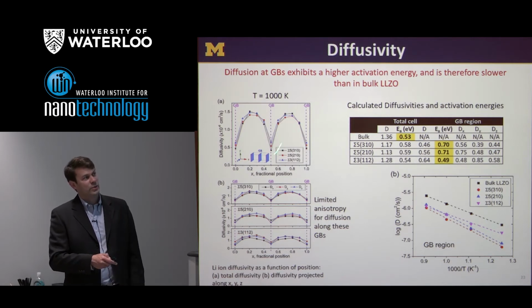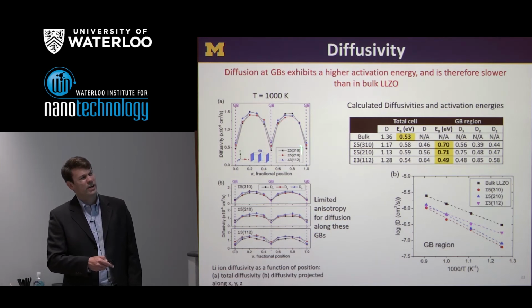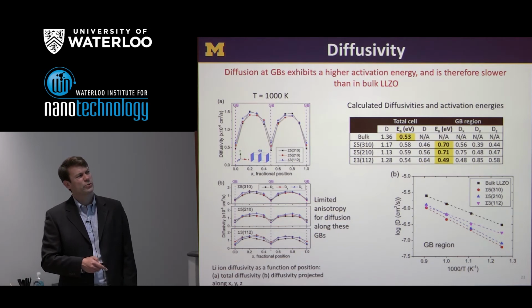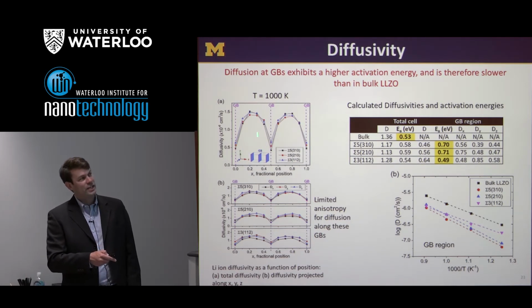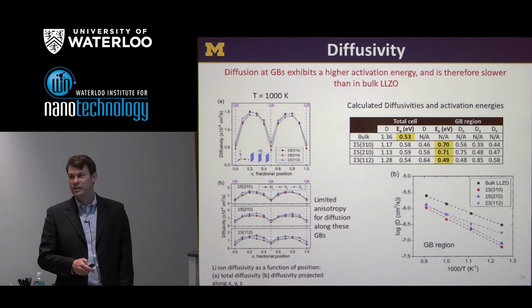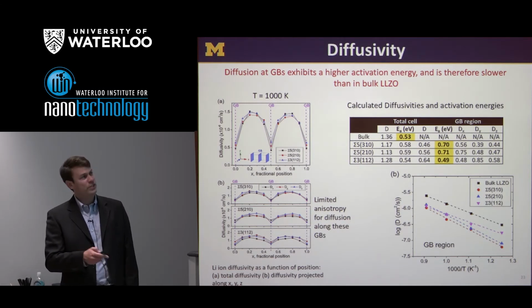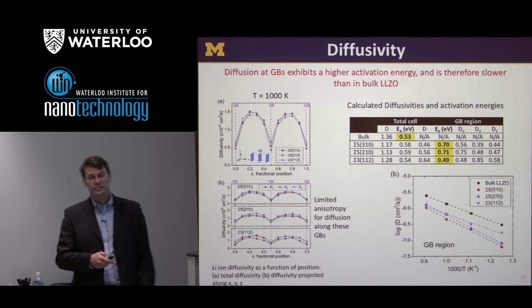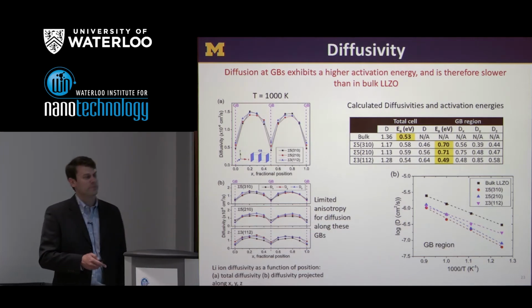And of course, we can evaluate now the diffusivity as a function of position. And so this is the total diffusivity of the 3 different grain boundaries. Again, remember the grain boundary planes are here on the edges, and there's also one in the middle. And at 1,000 Kelvin, there is obviously a difference, a reduction in the grain boundary diffusivity, but it's not a huge effect. This is only about a factor of 3. So that's not a huge penalty, at least at this temperature.